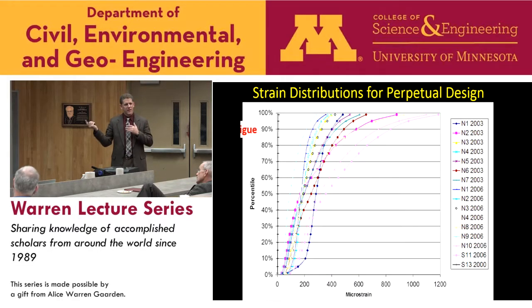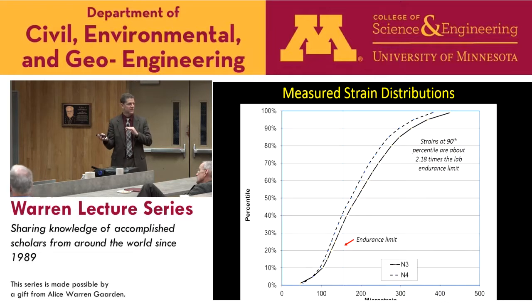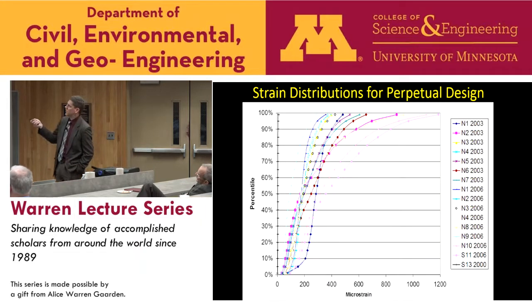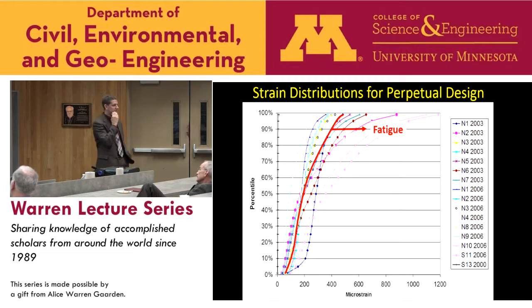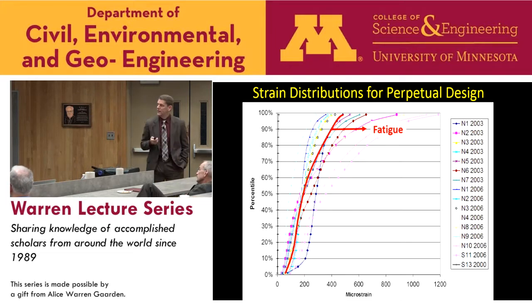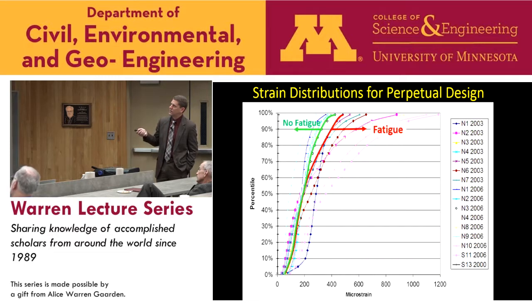We said, well, if we saw that here, what about all of our other sections? Some have cracked, some haven't cracked. If this is going to hold true, maybe we ought to see a difference in their strain distributions. And so this is a whole bunch of different test sections from the track. Again, cumulative percentage, microstrain. And what we found was that everything on that red line or to the right had bottom-up fatigue cracking. Everything on or to the left of that green line is no fatigue.